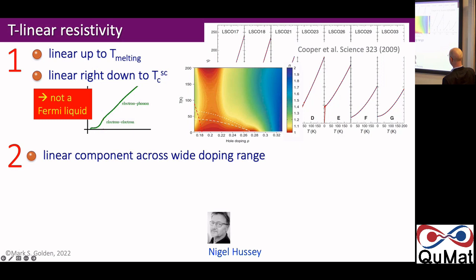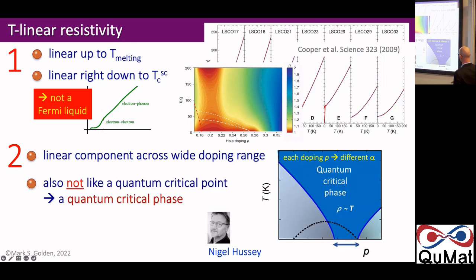So it's linear right down to TC, and there's a linear component over a wide doping range. So what we discuss is what we call a quantum critical phase. So there's a whole area of doping down here, which is above the optimal doping, the right-hand side of this superconducting dome, where all of these different doping levels look quantum critical, but they all have different power law scales, as you can see here. So this is really an area of phase space in chemical compounds, but that means in Hamiltonians, which are all looking quantum critical. So it's not an infinite number of single quantum critical points we can look at one after the other. We have to describe this quantum critical phase. So this is what the strange metal is.